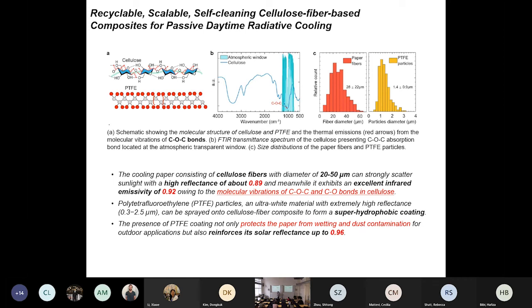So with the PTFE coating, we demonstrated that this not only protects the cooling paper from contamination by dust or other materials, but also reinforces the solar reflectance from 89% up to 96%. So it's really good, we demonstrated it. After we demonstrated this experimentally, the next step to make it commercialized is another story.